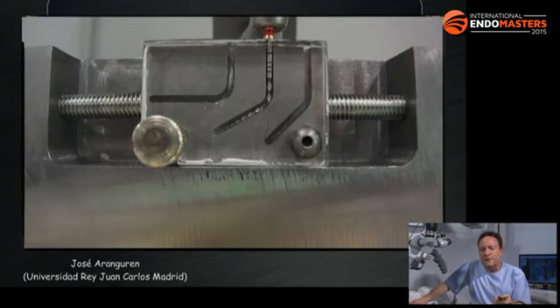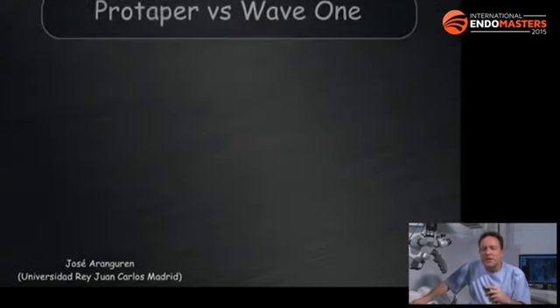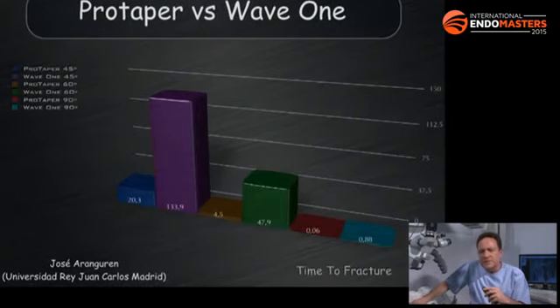And well, if you compare in this case Pro-Taper versus Wave.One, you will see that you have a comparison at 45 degrees between Pro-Taper and Wave.One, a comparison at 60 degrees, and a comparison at 90 degrees. First thing you see is that whenever you reciprocate, you live longer. It's not only reciprocation, because at the same time, don't forget that Pro-Taper has a different alloy. Pro-Taper is, I would say, conventional nickel titanium. Wave.One is nickel titanium M-Wire, so that will play a role.